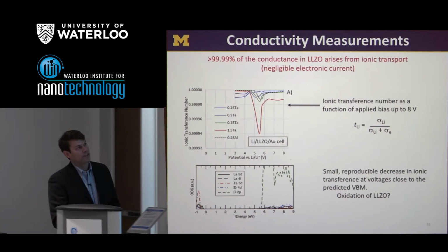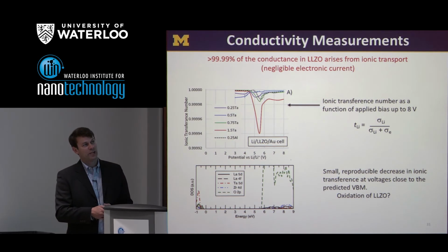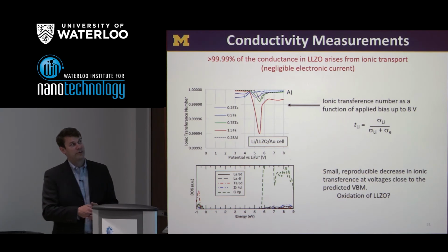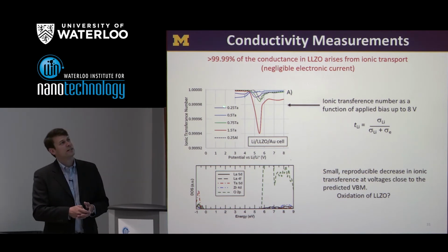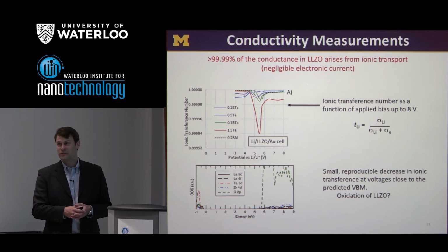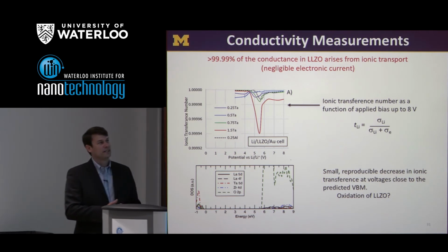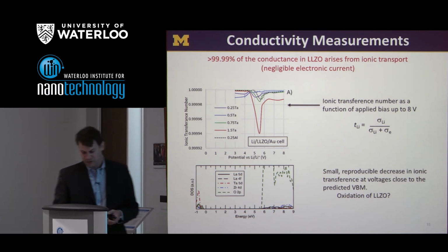Some other experiments were done to look at the electronic transport through LLZO. I'm just going to cut to the chase here and say that LLZO is an excellent electronic insulator. More than 99.99% of the current is due to ionic transport. So again, another data point in favor of it being a promising solid electrolyte.